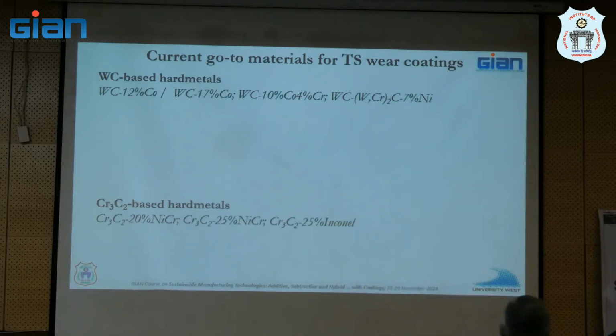If you look at tribology and wear coatings, and I'm happy if someone wants to argue with me about that, the only material that comes to mind is tungsten carbide, yeah? For any thermal spray coating industrially used, what comes to mind is tungsten carbide. Chrome carbide comes a distant second. When do you think of chrome carbide? When you're thinking about higher temperature application, because tungsten carbide can be used only till about 500 degrees or something like that. Beyond that, you cannot use it, right? So if you're looking at higher temperature wear, you consider chrome carbide, otherwise not, yeah?